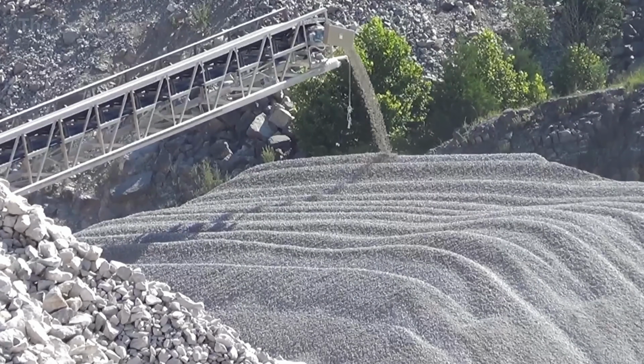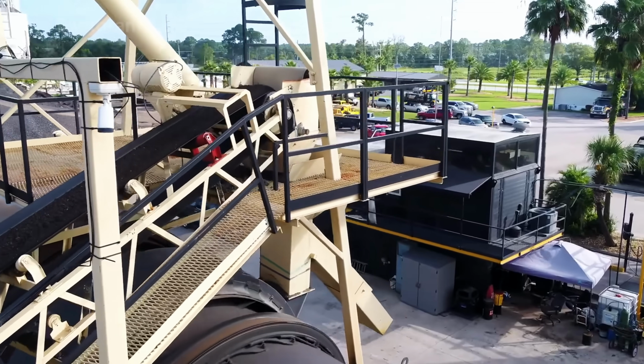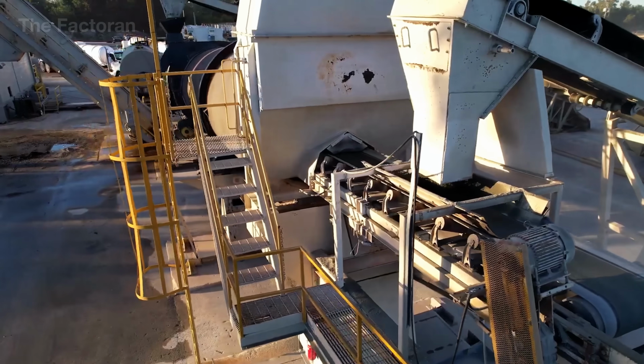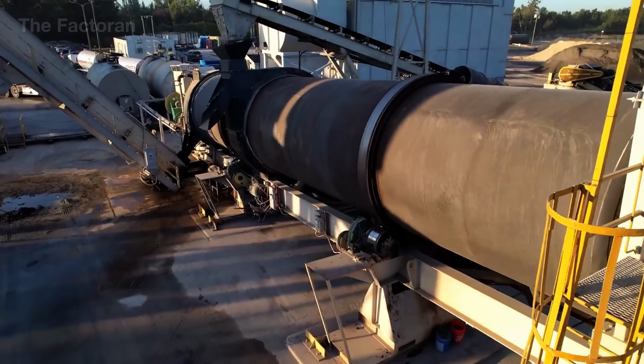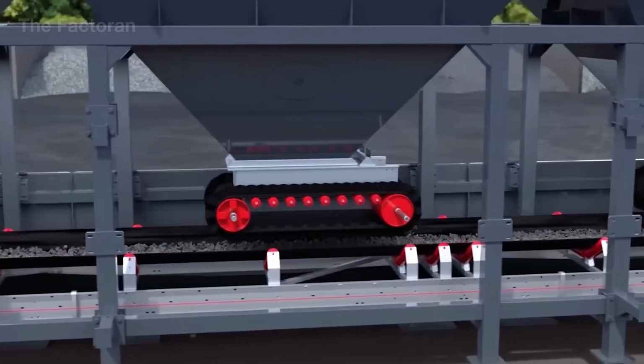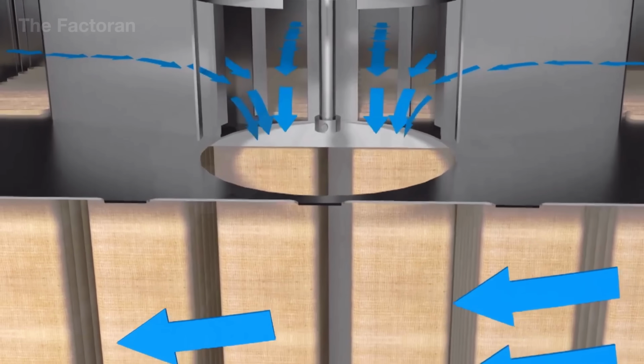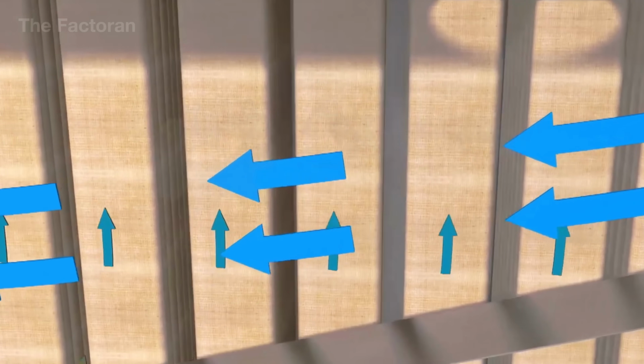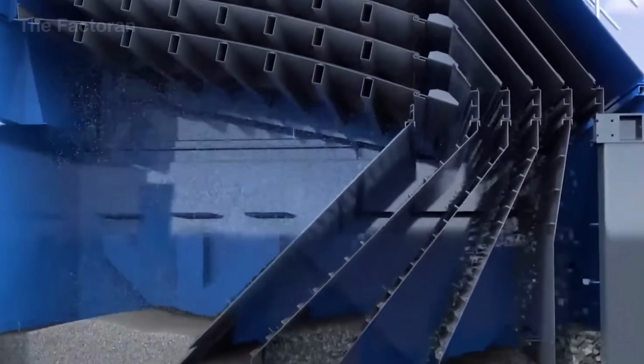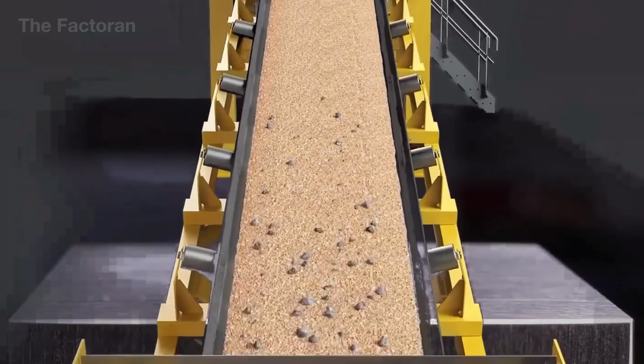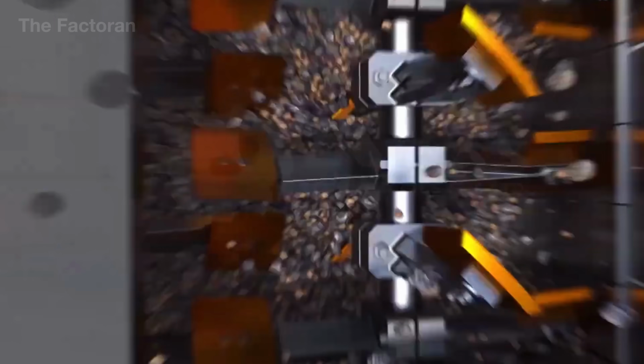When crude oil has been distilled to obtain the heavy fraction, and stone aggregate has been crushed and screened, both converge at the asphalt mixing plant, the place that defines the final quality of asphalt. From storage bins, aggregate is discharged onto steel conveyors and carried into a rotary dryer stretching dozens of meters long. Direct flames heat the material to over 300 degrees Fahrenheit, about 150 degrees Celsius. Inside, the aggregate tumbles continuously within the rotating drum, while high-powered fans draw out every trace of moisture, ensuring each stone is completely dry before blending.